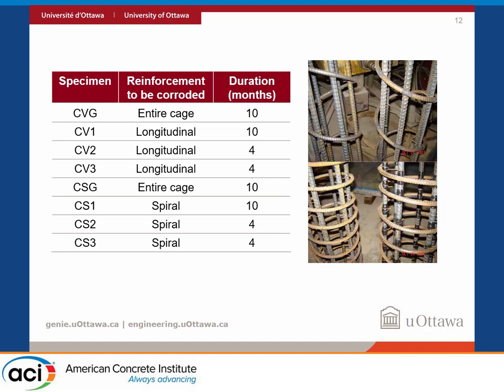So, as I mentioned, half of the columns had the longitudinal reinforcement corroded, some of them for 10 months, some of them for 4 months. The CS type of columns had the spiral reinforcement corroded, and then there was one of each type where the entire cage was corroded. When we wanted to corrode just the longitudinal or spiral reinforcement, we had to isolate the reinforcement.